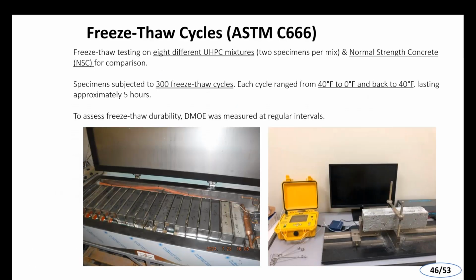Also, our colleagues did some more work, not necessarily related to corrosion, but concrete durability. With the UHPC developed and used here at FIU for many of our projects, we're looking at the freeze thaw frost resistance of our material, and we have here the freeze thaw chamber, and looking at some of the testing afterwards to identify the material itself and its degradation.